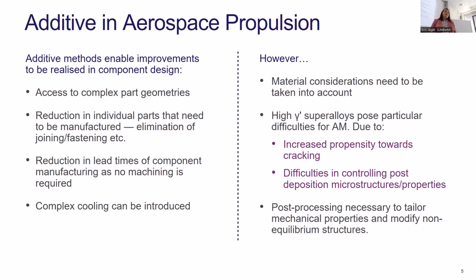But when we start thinking about the material that we're using, nickel-based superalloys are particularly problematic in that the higher the volume fraction of the gamma prime, which is the strengthening precipitate, so what we use for the mechanical performance and the temperature capability, the worse it is for additive manufacturing. So we have increased propensity towards cracking, and we find difficulties in controlling the microstructure the higher the gamma prime content as well. But post-processing is necessary to tailor the mechanical properties and modify those non-equilibrium structures as well.